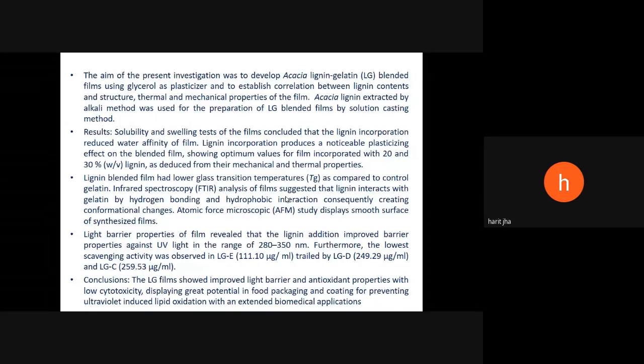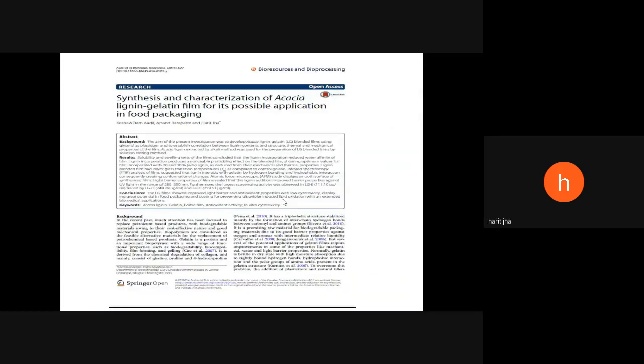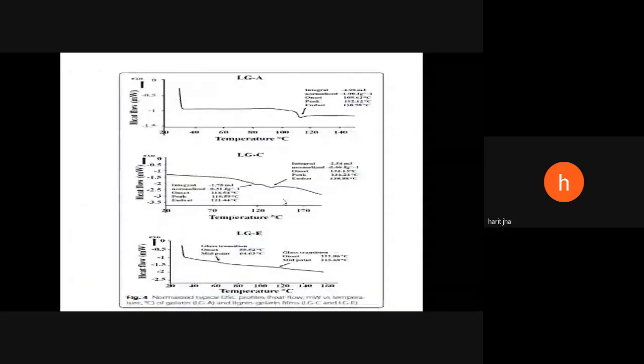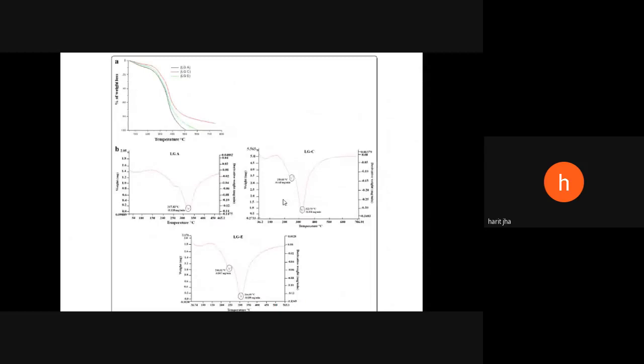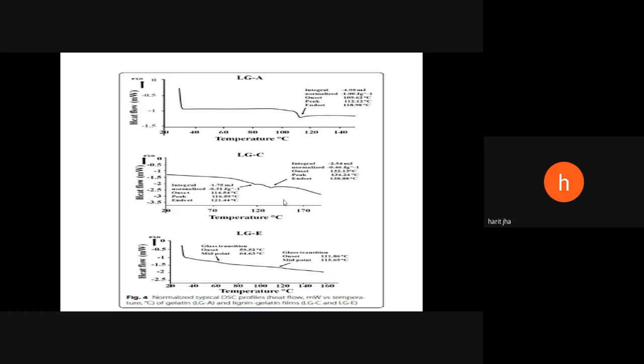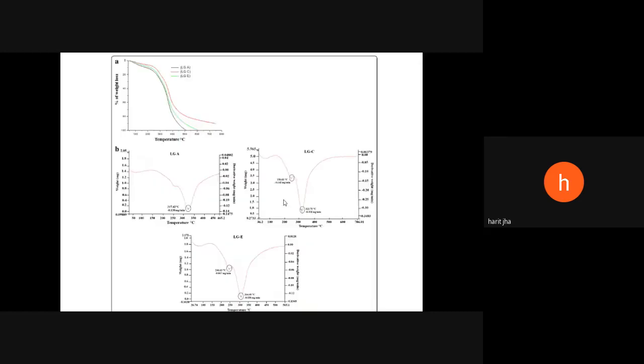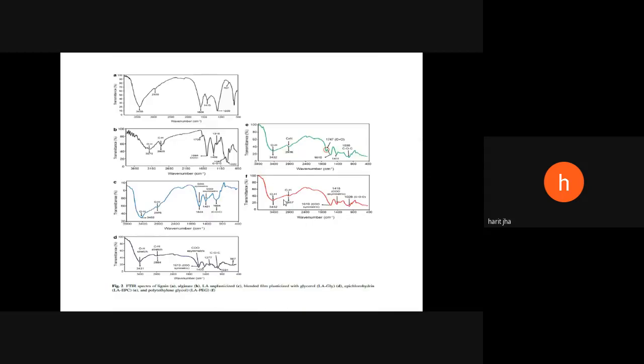The lignin gelatin film shows improved light barrier and antioxidant property with low cytotoxicity and displays great potential in food packaging and coating for preventing ultraviolet induced lipid oxidation, and with an extended biomedical application. So this is the work we have done with the gelatin, and then these are some of the work. Okay, this is the TGA, this is the DSC profile of those films, TGA profile, then FTIR spectra.